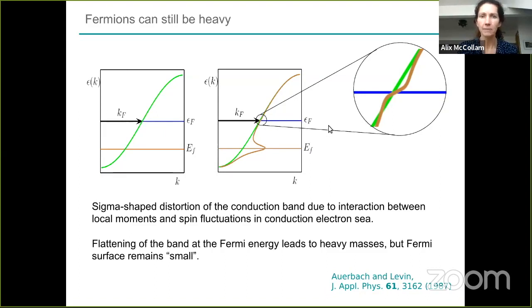So although the Fermi wave vector is unchanged, so the Fermi surface doesn't change size, you can still have a renormalization of the masses. Even when you're not in the Kondo state, you can still have rather heavy fermions due to this type of renormalization of the band, this flattening here of the band at the Fermi energy. So there are many ways to get a heavy fermion.